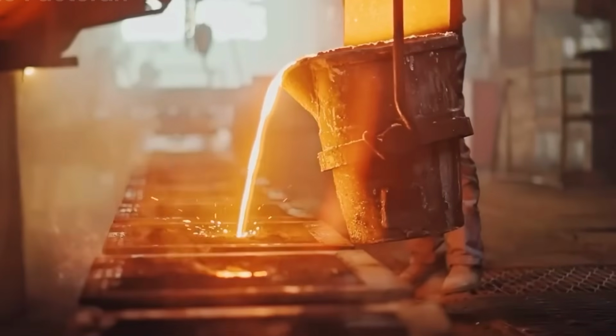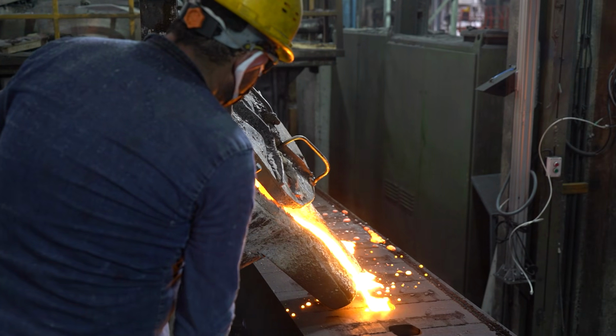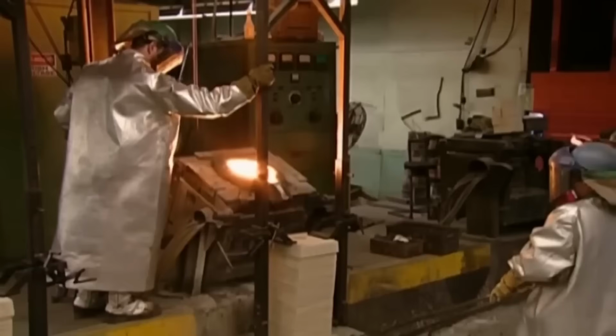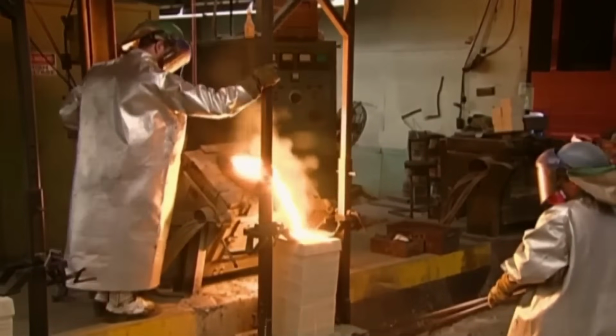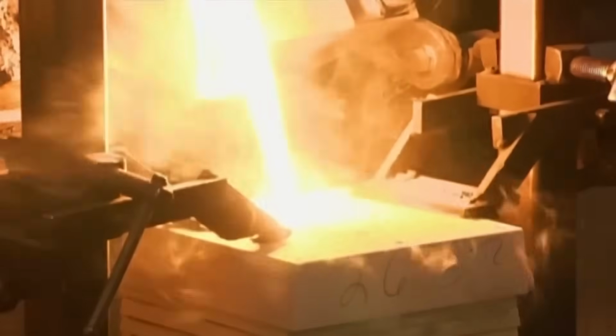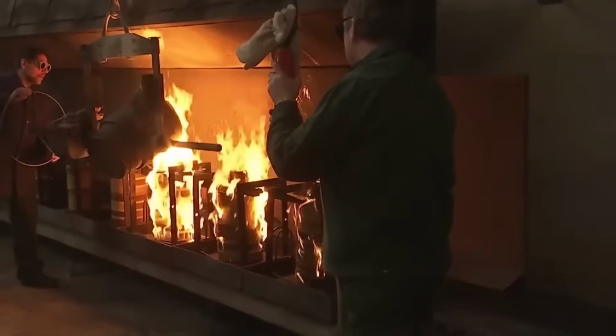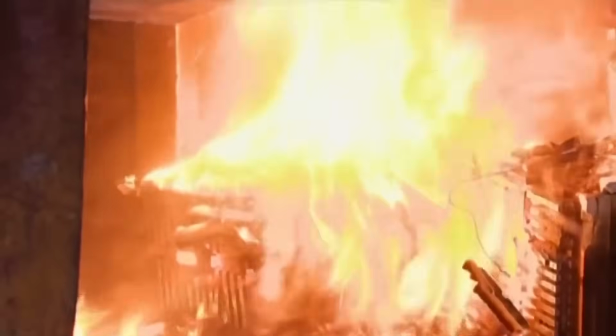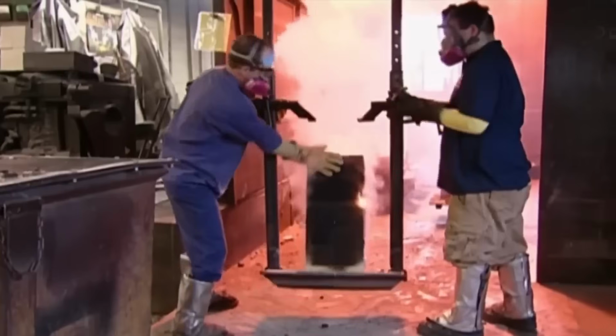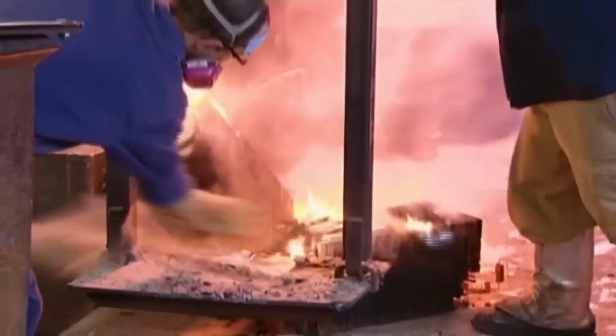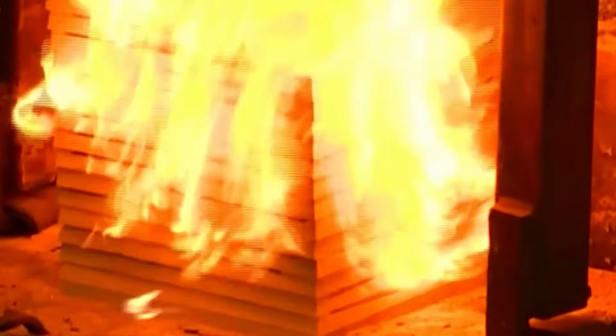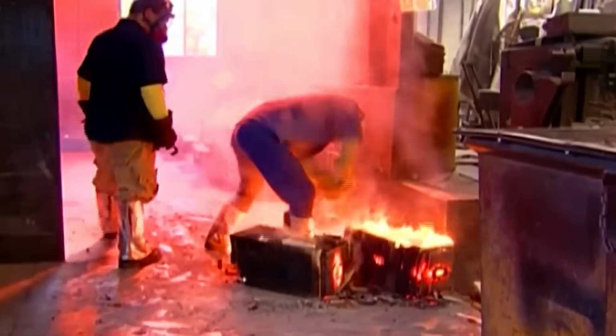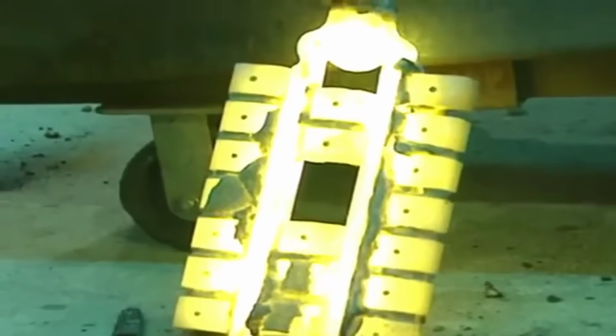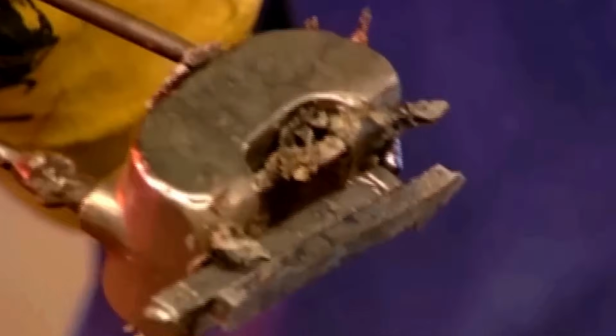The resulting liquid metal is carefully poured into the sand molds, filling every cavity and reproducing every detail of the design. The pour is carefully controlled to prevent air bubbles, cracks, or internal defects. The molds catch fire during this process, since the gases used to harden the sand are highly flammable. They're transported to another section of the foundry and set down on the floor to cool. Cooling is carefully controlled to prevent internal stress, cracking, or deformation. Once the metal is fully solidified, the sand mold is broken apart to release the metal piece.